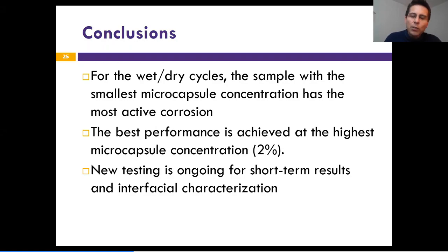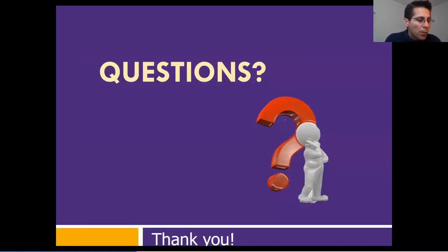We are very good now in terms of one month. We can tell in one or two months. In the standards, we have 1.5 years of corrosion testing to see if an additive is good or bad. But I think that we can say that in two months we can tell if a microcapsule or anything added to the concrete is good or bad in terms of corrosion. So we also want to make this a conclusion: the testing that we are doing is getting good results.